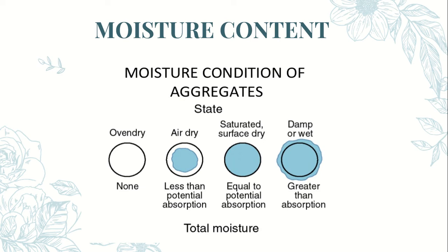Due to the sealing of pores of aggregates in the concrete, the absorption decreases, so the extra water should be added accordingly rather than based on the 24 hours absorption rate. Another important factor is that if we add moist aggregate into concrete, it will add water to the concrete, and if we add dry aggregate, then it will absorb water from the concrete. Hence corrective measures should be taken for both, otherwise the water cement ratio will get affected.